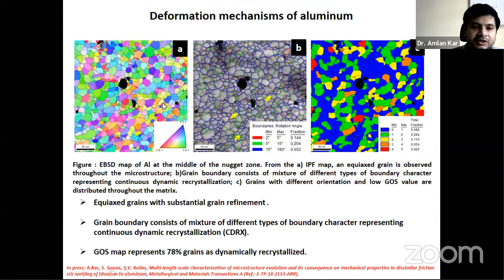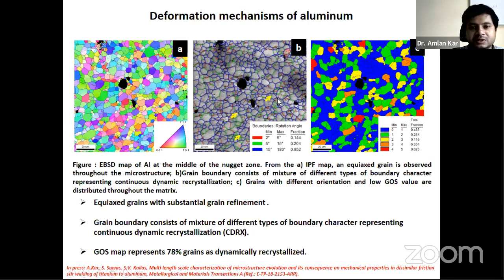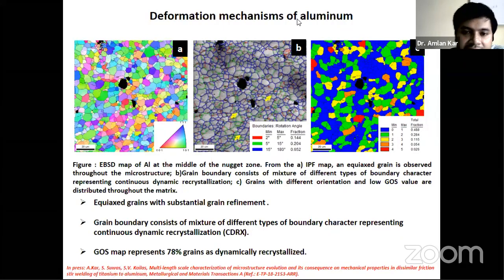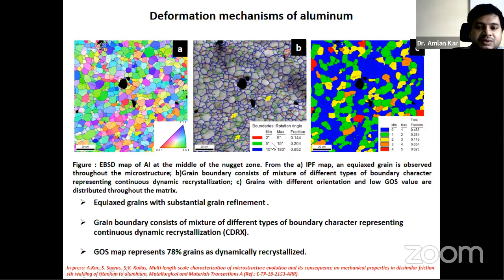In the aluminum side, we have seen a very good, well recognized recrystallization microstructure. From here, we can see a few grains. We have already marked the grain boundaries. Three types of grain boundary are possible. This is a low angle, sub-angle grain boundary. This is a low angle grain boundary. This is a high angle grain boundary. Any grain surrounded only by high angle grain boundary we can call a grain, a complete grain. Here you can see there is no complete grain as such. There is a development of the grain, and during the formation of the grains, there is a development from the sub grain to the low angle to the high angle grain boundary.